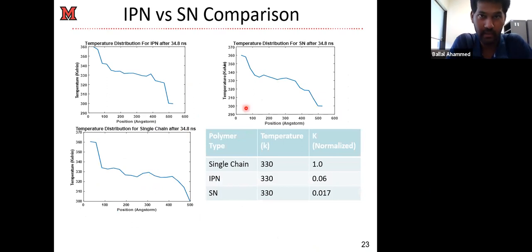In our case, we compared three cases: a single chain, just a single chain, then the IPN polymer and the SN polymer. For the three cases, you see the temperature distribution. If I extract the thermal conductivity, normalized in terms of a single chain, you see that the single chain has 2 orders of magnitude higher thermal conductivity than the IPN and the SN. And the IPN has almost 3 times higher thermal conductivity than the SN materials. The single chain having higher thermal conductivity is very expected.